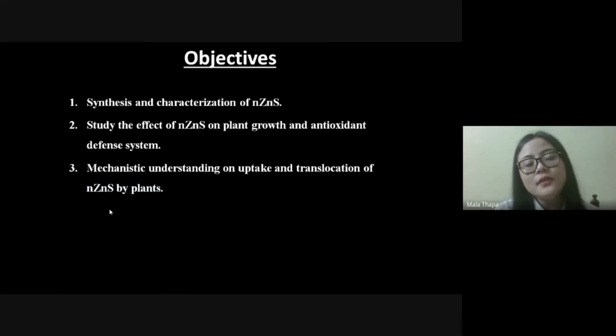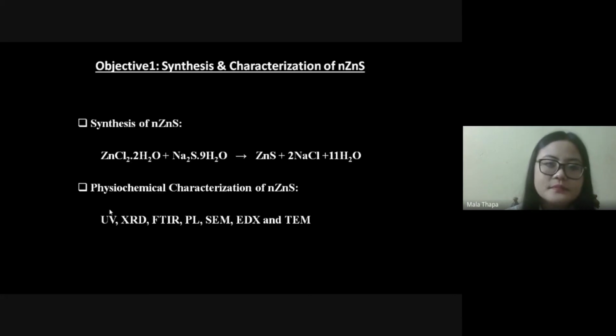Therefore, the objectives of my studies are synthesis and characterization of zinc sulfide nanoparticle, studying the effect of zinc sulfide nanoparticle on plant growth and antioxidant defense system, and finally, understanding the mechanism of uptake and translocation of zinc sulfide nanoparticle by plants. We have synthesized zinc sulfide nanoparticle by chemical precipitation method, and this is the formula for synthesis of zinc sulfide nanoparticle. And after synthesizing zinc sulfide nanoparticle, we have characterized the particle with UV spectroscopy, XRD, FTIR spectroscopy, PL, scanning electron microscope, EDX, and transmission electron microscope.